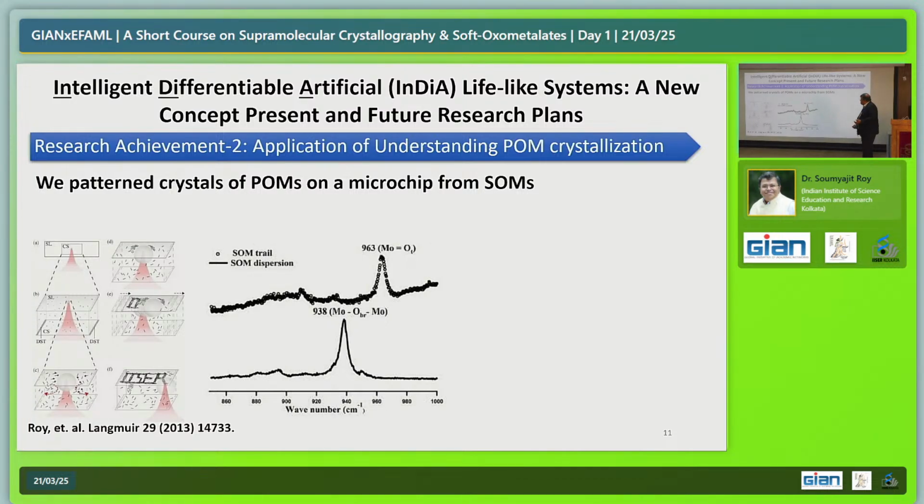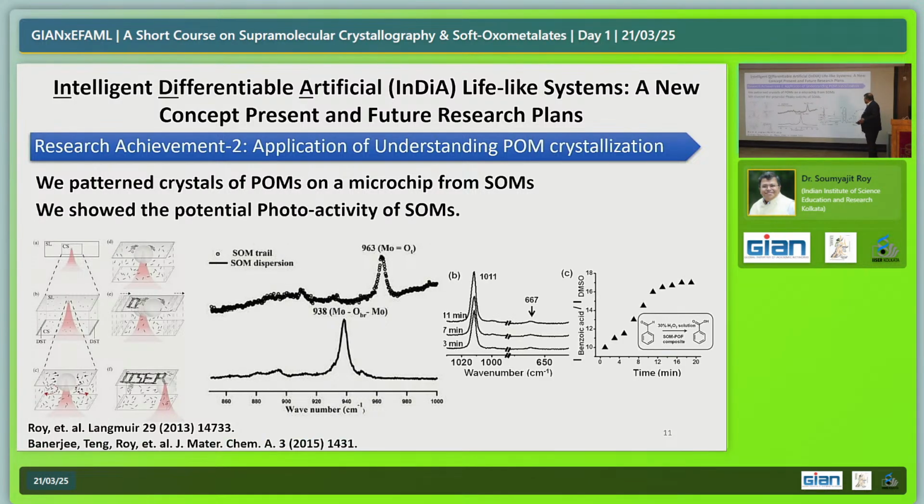So then we were able to show with Raman spectroscopy that indeed you have a transition from the breathing mode of these vibrations, which are on the sides of these nanotubes, towards the more crystalline domain. And then we also did a study where we were able to convert benzaldehyde to benzoic acid on these trails. So we not only formed the trail, but also we did catalysis with this, right? And benzaldehyde was oxidized into benzoic acid, and this showed a sigmoidal curve.